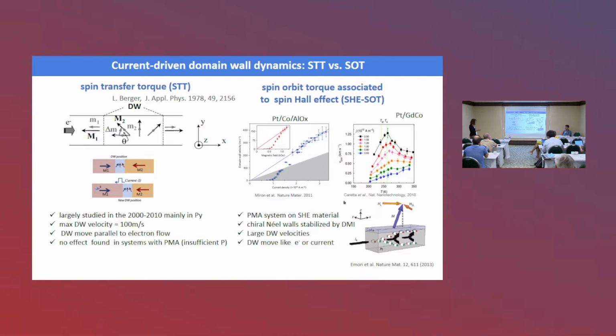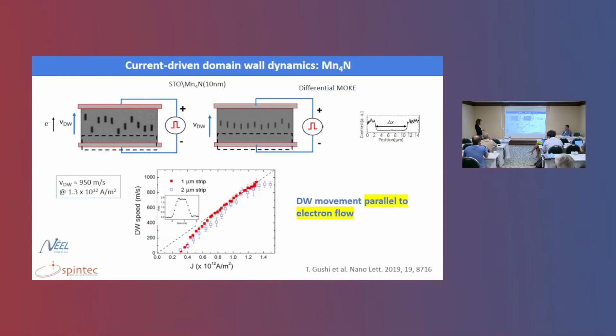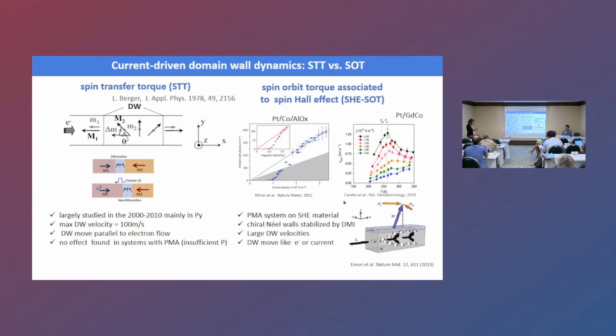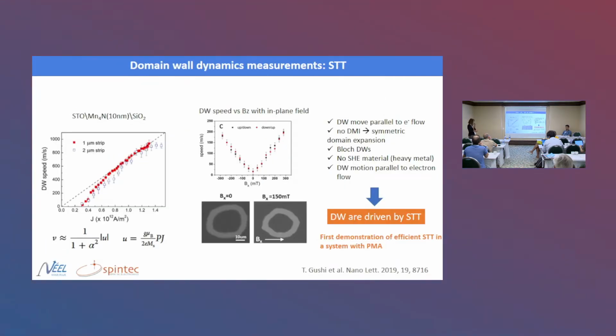So in our case, domain walls move, is it this one? Yes, no. Moves in direction of electron flow. So we were convinced that spin-transfer torque is the phenomenon that drives the domain walls. But to completely exclude the presence of spin-orbit torque, we also measured DMI in this system. So we did domain wall speed measurements driven by an out-of-plane field in the presence of an in-plane magnetic field. And we saw that the domain walls moved symmetrically in the presence of the magnetic field.